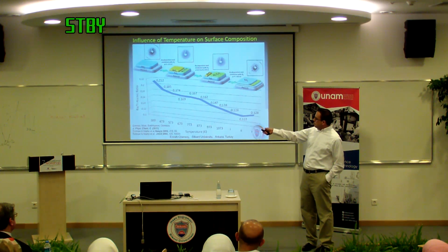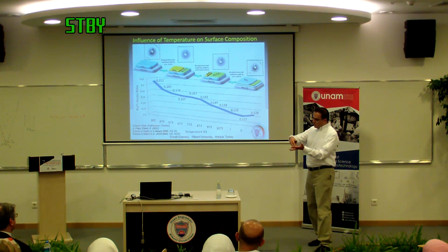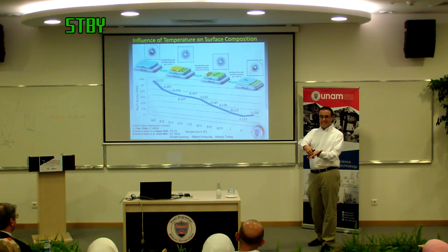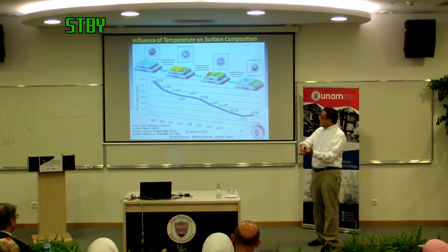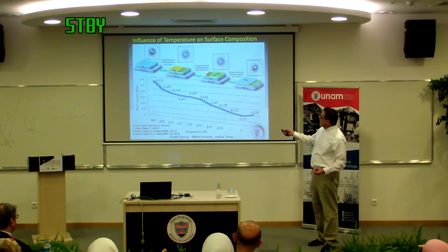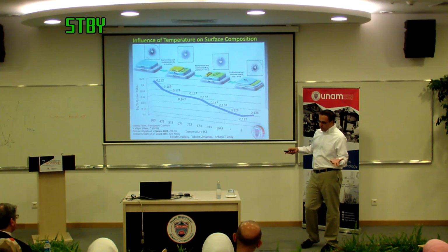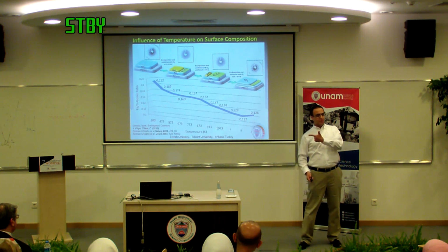a titanium-enriched surface. So it's obvious that barium oxide, if you just heat it up, makes mixed oxides and forms, for instance, titanates and perovskites and probably spinels, and it goes inside the titanium, and the storage domain, the domain which stores the NOx, your active storage site, is lost. So one of the possibilities for thermal aging in the presence of titanium is probably this kind of mechanism.